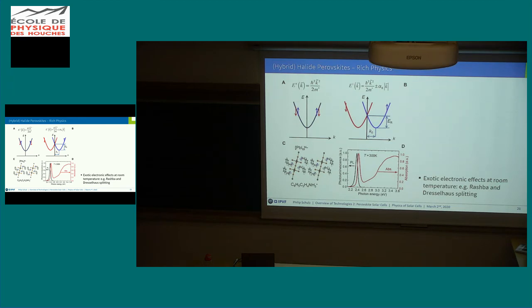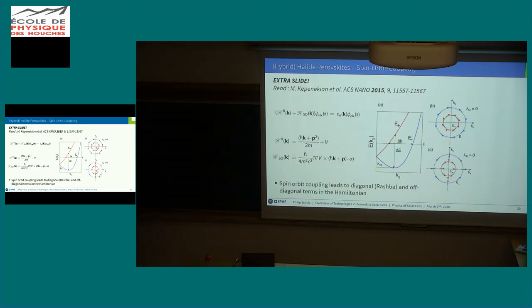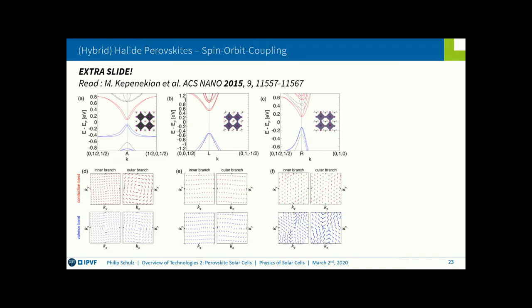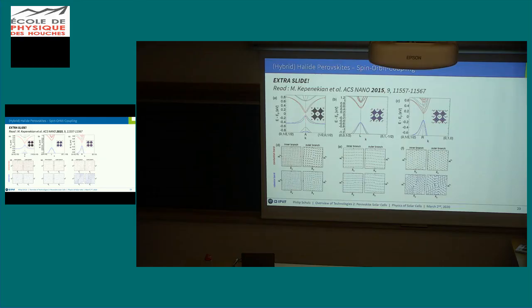decks of slides, but maybe just one very small point about the rich physics in perovskites. Here you can see the dispersion relation, energy versus k vector of a quasi-free electron. Now, this is how you could describe the conduction band in a perovskite, also the valence band on the other side. Once you start exciting the perovskite, you can see a split of these bands into Rashba split components. So you get an additional term for your eigenenergy values that is coming from spin orbit coupling. This has been seen particularly for 2D perovskites, where you even see excitons at room temperature, but it also occurs in 3D perovskites, and this is seen here, where you see the split of the valence and the conduction band.